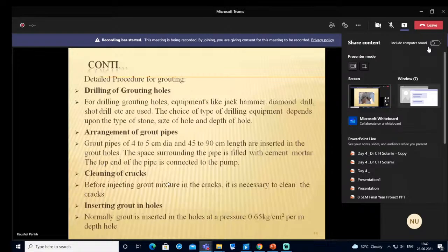Finally, the cracks must be cleaned before injecting the grout mixture so that a proper bond can be achieved. Then we have to insert the grout into the holes with a certain pressure, specifically 0.65 kg per cm square per meter depth of hole.